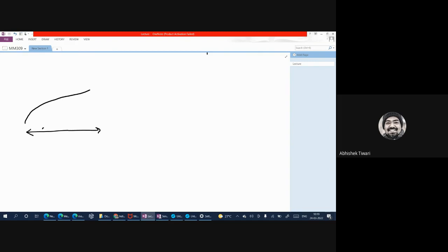Similarly, the time dependence and temperature dependence of materials, it's not that in metallic materials you will not see it. It's just that the time scale to see any time dependent deformation, at the temperature we live in on this planet, for metallic material will be very large in comparison to polymeric material. So it's just a difference in scale. A polymeric material will deform even at room temperature. So if I apply a constant stress on a polymeric material at room temperature, then you will see the exact same creep kind of deformation which you would see in metallic material at elevated temperature.